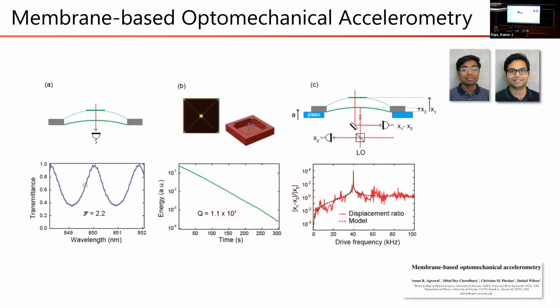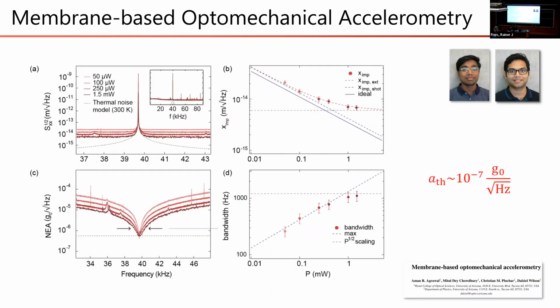By very simple, it's just a simple etalon. It's monolithically stable and beautiful. And the quality factor of the mechanical resonator is above 10 to the 7. So this is a very nice, simple system. We can achieve sensitivities around 100 nanoG. By the way, G is the local gravity, at 40 kilohertz, limited by thermal noise over a bandwidth of maybe a kilohertz.